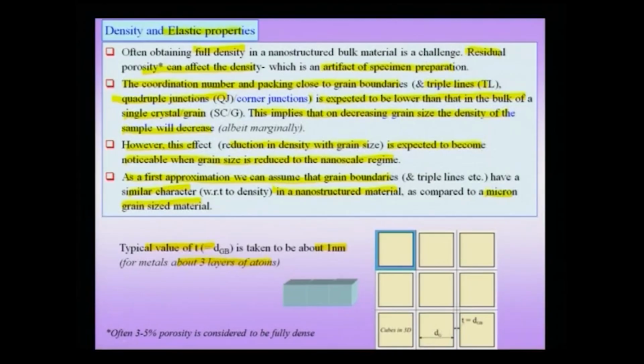So, to proceed further, we will make some assumptions. Number one is that the grains are all cube shaped, which is of course a very drastic assumption, because, as mentioned, the closest they can actually come to is something like Kelvin's tetrakaidecahedron and definitely not close to a cube. The second assumption is that the character of the grain boundaries, the triple lines and quadruple junctions, does not change as we go from a micron size material to a nano size material. The third assumption is that the grain boundary thickness, which is the region of disturbance around a grain boundary or a triple line, is of the order of 1 nanometer. Making these assumptions, we will go ahead and make a model to calculate the fraction of grain boundaries with decrease in size.